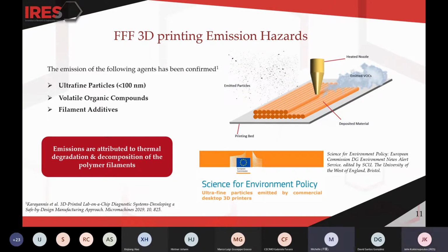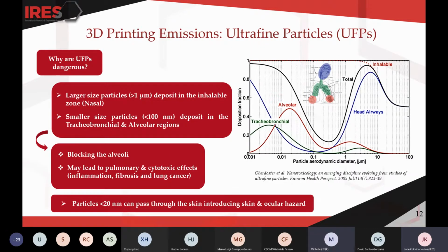If we go on, we can concentrate on ultrafine particles, and we can see that concerning UFPs, the respiratory tract is the main exposure pathway, and deposition of particles in the lungs highly depends on the ultrafine particles' aerodynamic diameter. According to Oberdörster et al. and multiple path particle dosimetry clearance models of inhaled particles that you can see in the picture, larger particles over 1 micrometer tend to deposit mostly in the inhalable, we say the nasal, zone, whereas smaller particles below 100 nanometers deposit in the tracheobronchial and alveolar regions of the lungs, deeper in the lungs.